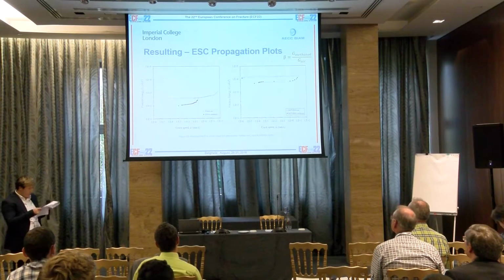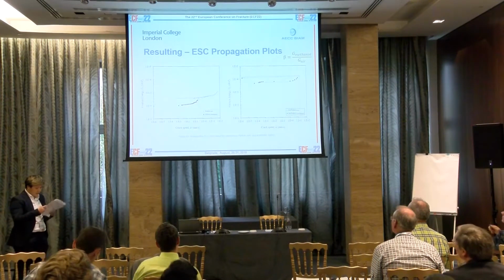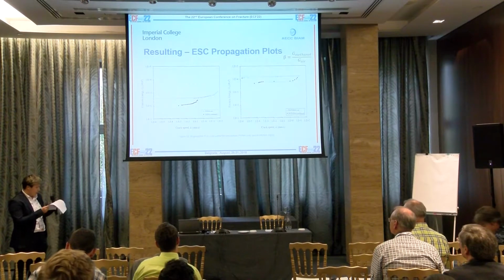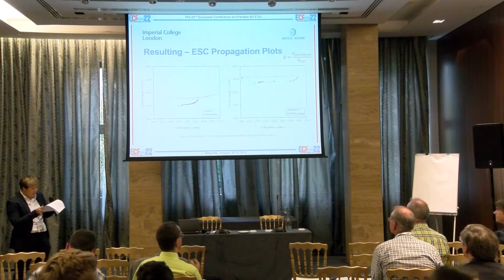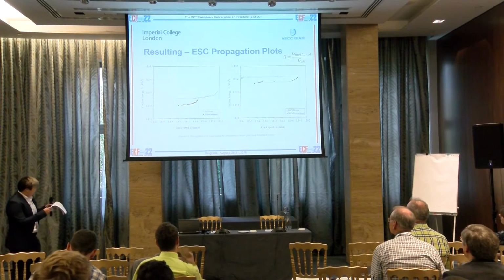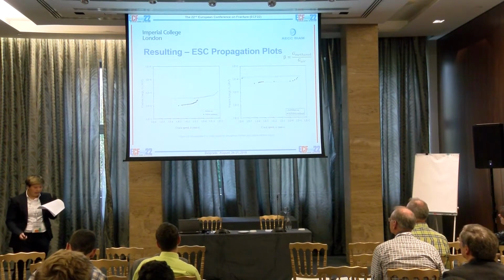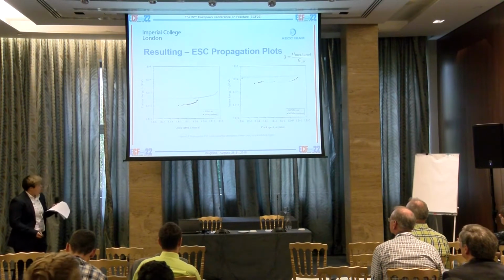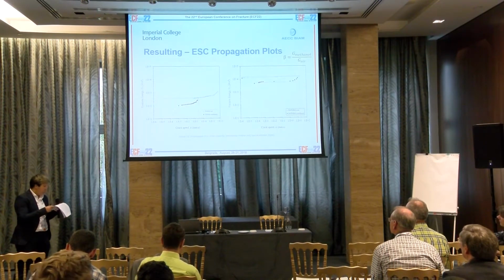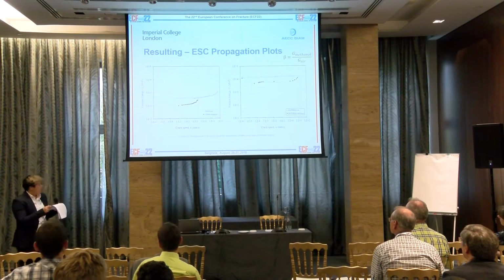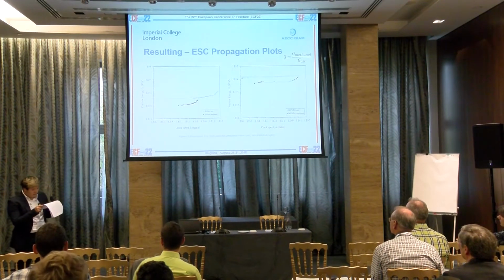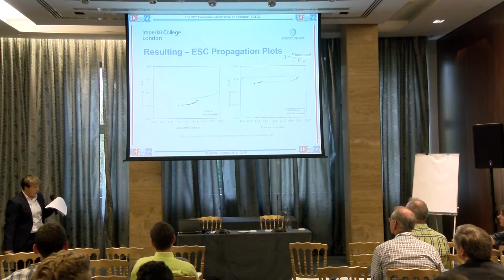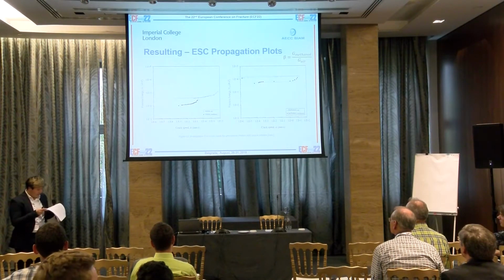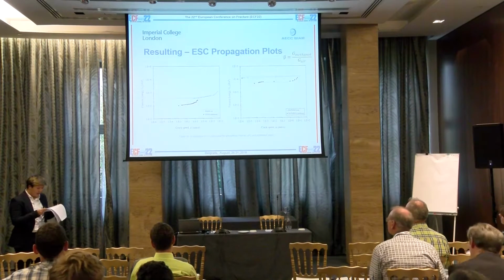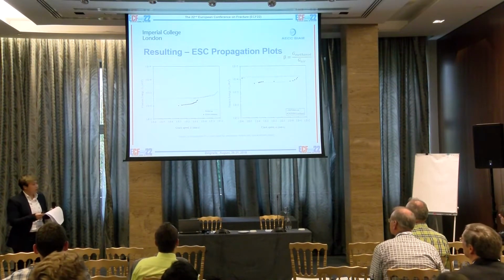Here we have the ESC propagation plots for both amorphous and biaxial PMMA. On the x-axis, we have crack speed, and on the y-axis, we have fracture energy. The intersection points of the in-air and in-environment curves indicate the value of critical crack speed and the corresponding fracture energy. Once the crack is initiated, the energy required to propagate the crack in methanol is lower than in air until it becomes flow controlled. Above this critical point, the availability of the environment becomes the limiting factor. Thus, the crack growth in the environment is equivalent to in air. This happens at the intersection points of the air and methanol curves in the plot.